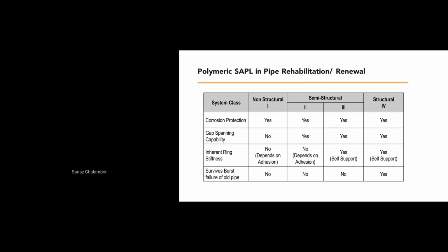Polymeric SAPL in pipe rehabilitation and renewal can be used in different stages of the pipe lifetime. So when the pipe is new, when manufactured or just installed, we can apply the system inside the pipe, fully bonded in very thin layers to protect the pipe against corrosion and deterioration. So we can apply non-structural corrosion prevention only.